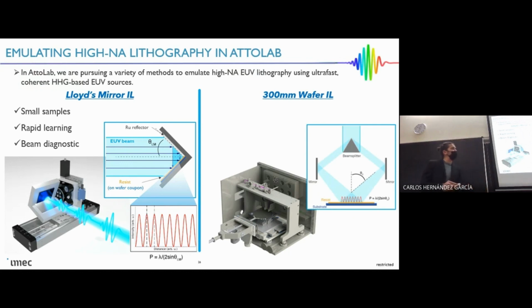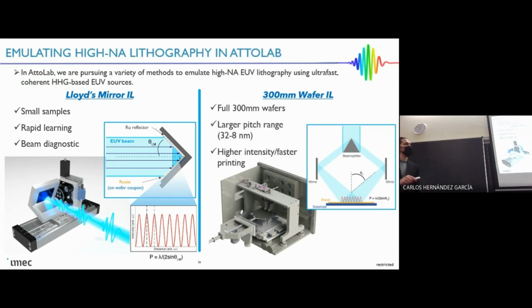We're actually going to split the beam first using a coated prism, and then recombine the beams back on top of each other on the photoresist. And the reason for doing this is that it's flexible. It can change its pitch range over a much larger range than this simple device can. And because we're not using partial reflections, we're using the whole beam intensity, it actually prints a lot faster.